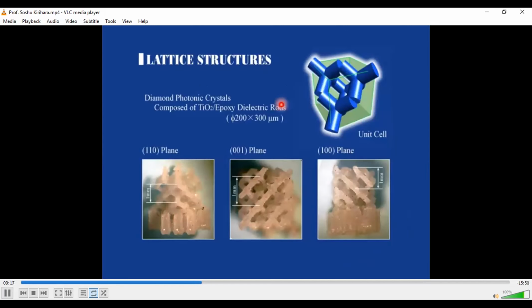This figure shows fabricated micrometer order photonic crystals made by a conventional stereolithography process. You can see the micrometer order lattice obtained. However, in this case, we used only a 0.1 millimeter, 100 micrometer spot size laser beam, so it is difficult to create micrometer order structures. And the most important thing, these are composite materials. The epoxy matrix absorbs the terahertz wave, so we have to create more clear micrometer order diamond type three-dimensional structures by using a perfect 100% ceramics lattice.